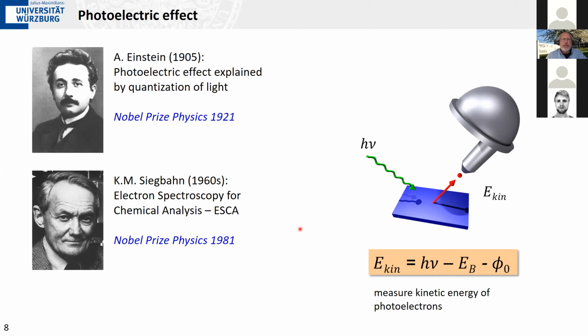This goes by the name of electron spectroscopy for chemical analysis, because this was applied mostly at the time to core levels of materials, and the core level energies, the binding energies of the electrons in the core levels, is element specific, and therefore the energy distribution of the photoelectrons gives you information about the chemical composition of the sample. This, by the way, was also awarded with a Nobel Prize in the early 1980s.